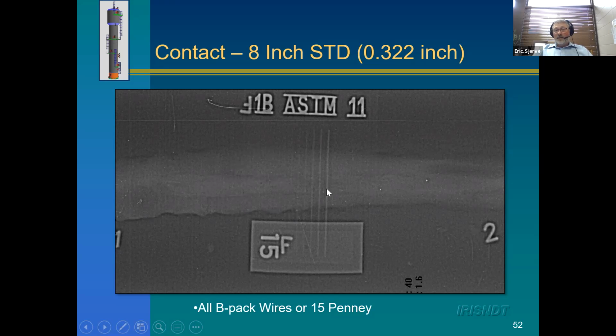And then this is our sensitivity. These are the wires on that penny. And we want to be sensitive to about 2%. We can just calculate it, right? 2% of that is what we want to be sensitive to. And this is an ASTM B penny. So there's a bunch of different wires. They don't all fit in one penny. There's 4 of them. There's an A penny, a B penny, a C penny, and a D penny. And this is the right one for the thickness of this inspection.